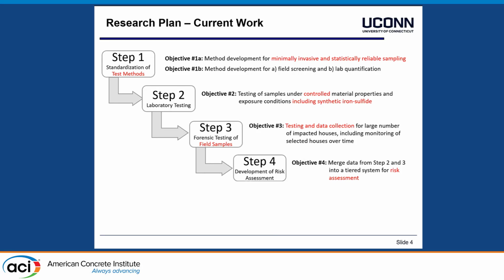Step 2, they are all interchangeable, is laboratory testing, where the idea is under controlled laboratory conditions, to mix concrete and then test those. This includes also the synthesis of a pyrrhotite as a controlled parameter in our mixes. Step 3 is field testing, so that we can apply our test method and build up a database so that we can compare apples with apples, and all 3 of those steps they merge into a risk assessment framework.